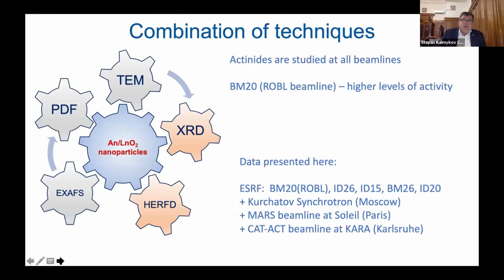So there's a combination of techniques that we use. Certainly this is wet chemistry, kinetic solubility studies under different conditions, and then examination by different methods, very local methods like high resolution transmission electron microscopy with selected area electron diffraction. And certainly the spectroscopic methods, starting from X-ray diffraction, HERFD, EXAFS, and PDF.